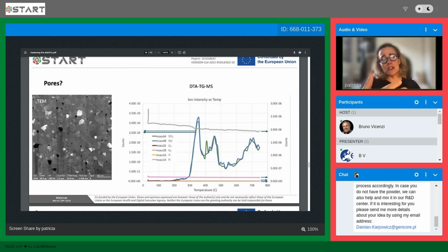But the issue is that above 300 degrees C, it will be very important to make sure that tetrahedrite is not exposed to air. And this has implications at the level of the fabrication of the devices, because it means that they need to be sealed. They cannot be in air, because otherwise you'll have oxygen diffusing in and you'll have the formation of gas, which in the long-term service of the devices will pose problems.